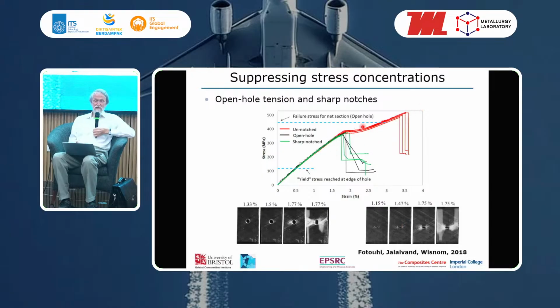So the red response is the unnotched response, and the green and the black are showing the notched response. And in both cases, the stress goes up to about the same level as it did in the unnotched case, and then it fails. So what you need to remember is that there's a stress concentration of about 3 around that hole, and so it's right down at this point here that the stress is reached at the edge of the hole, which could cause failure to occur. But it doesn't fail immediately, and as you go beyond that point, all the way up here, we're getting progressive fragmentation around the hole, and that is redistributing the load around the hole in the same way as plasticity in a metal would distribute the stress around a hole in a metal sample with a stress concentration. And by this point, we've got fragmentation across the whole specimen, and then it fails.